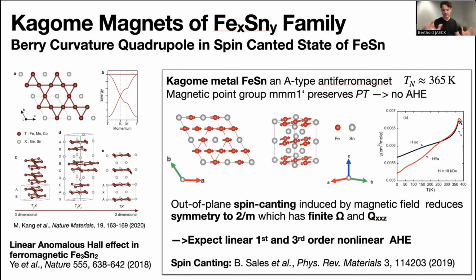More specifically, in this context of these multipole effects, it gives you an antiferromagnetic order along the out-of-plane direction. Iron tin, for example, is a so-called A-type antiferromagnet. It has a relatively large, above room temperature Néel temperature, and essentially stacks ferromagnetically ordered Kagome lattices with in-plane moments antiferromagnetically in the out-of-plane direction. Now, when you just look at a native iron tin compound, you'll find it has an mmm1' symmetry, which preserves the combined PT symmetry. So it's not expected to show any anomalous Hall effect.